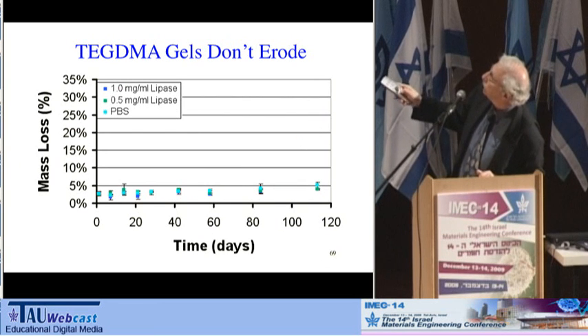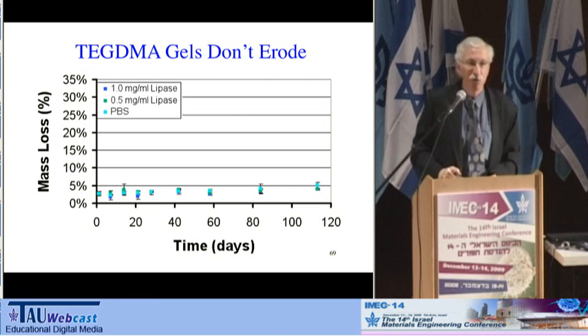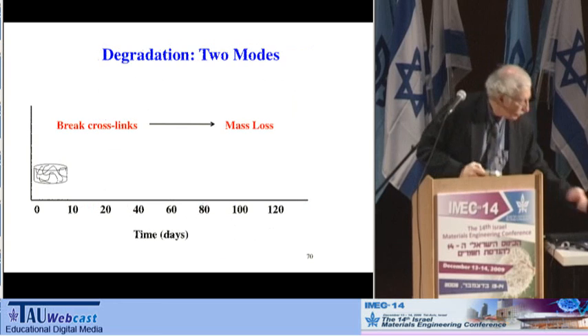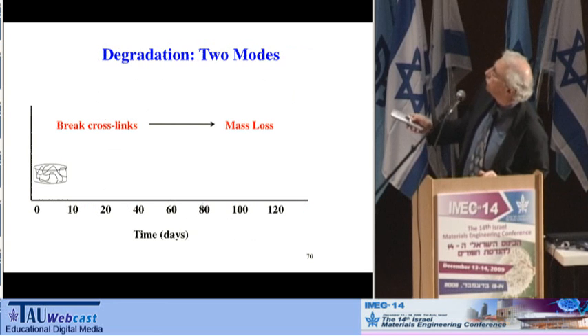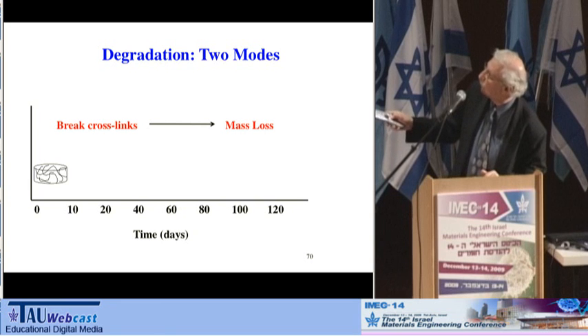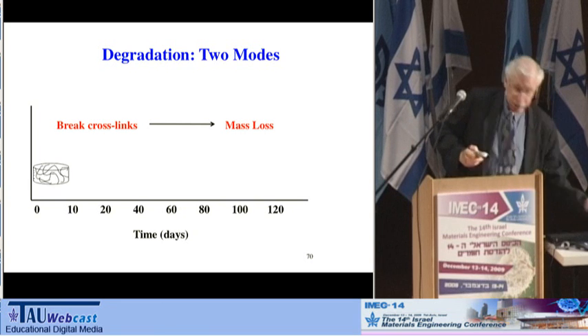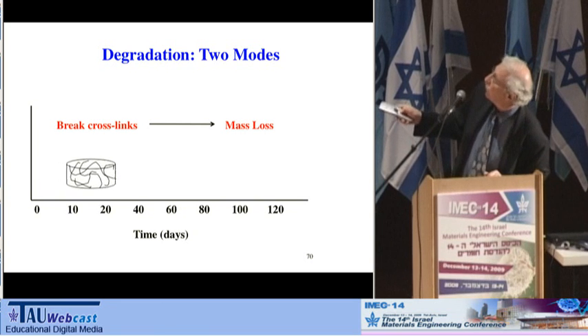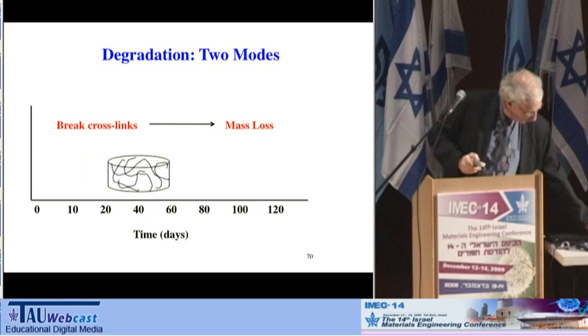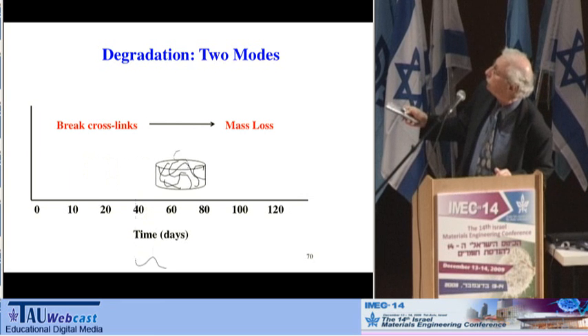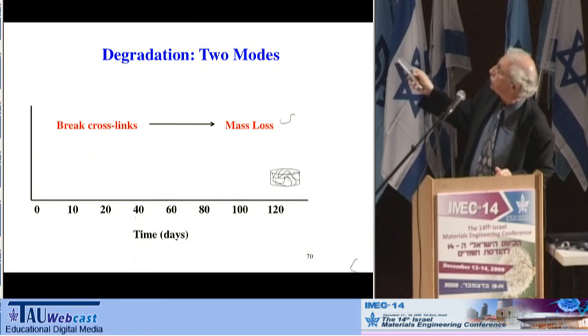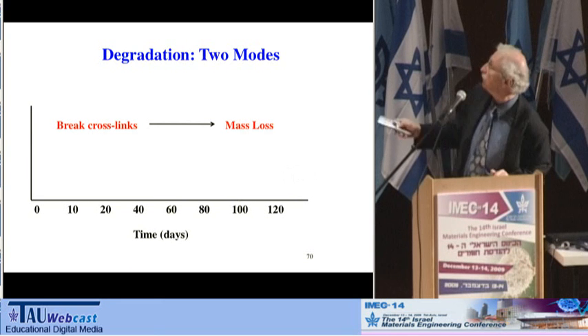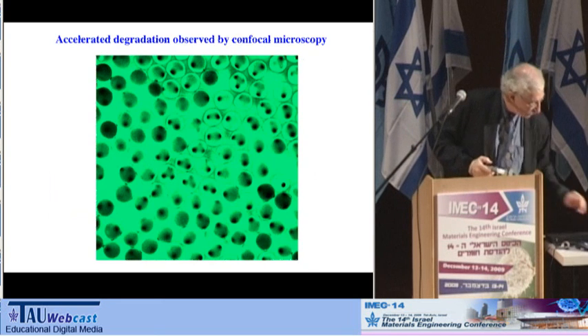Again, this is the non-biodegradable one, and basically it has no change over time. So what's going on here? Well, this is the process we think is happening. We have our cross-linked material, and at first we start breaking cross-links and it swells. And then we start breaking backbone units and we start solubilizing pieces out of it. So we think that's the mechanism that's happening.